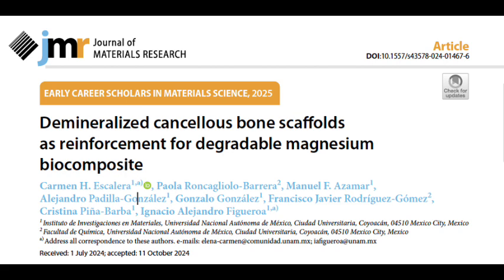Okay, so with the composite that had the thinner MgO layer, the fracture, it's a break? Yeah, it tended to travel along the interface. Between the MgO and the magnesium? Exactly. Like a clean break. Pretty much, yeah. And what about the composite with the thicker layer? That one was a bit more... Messy. So it didn't break as cleanly. No, it was more erratic. The cracks went through the MgO layer and the magnesium.